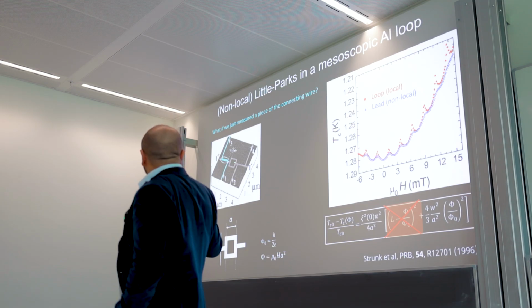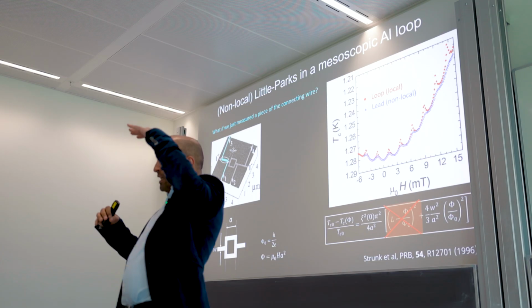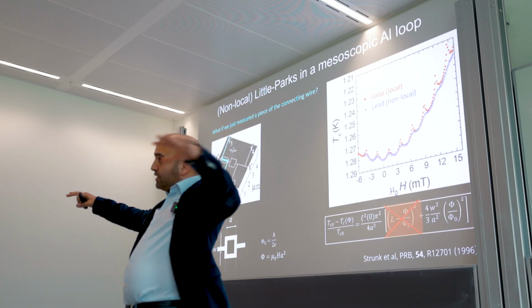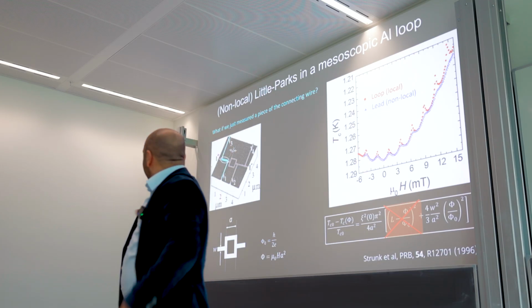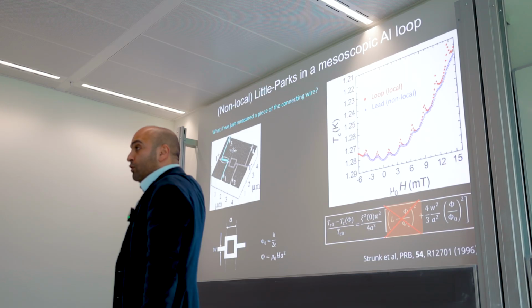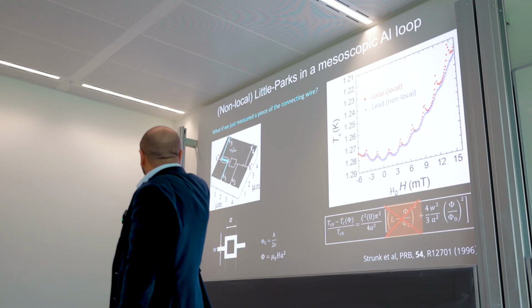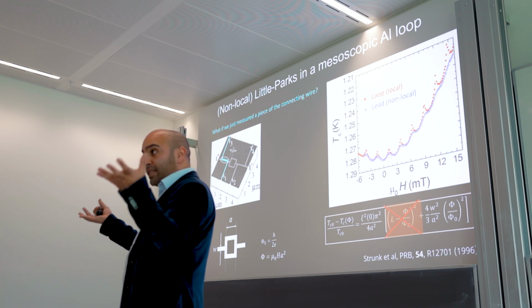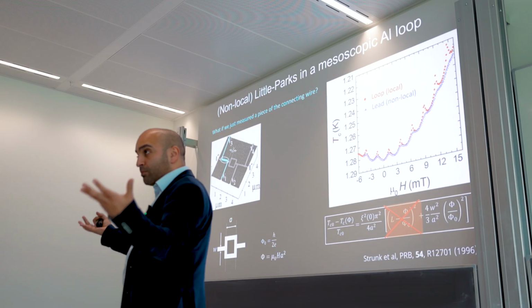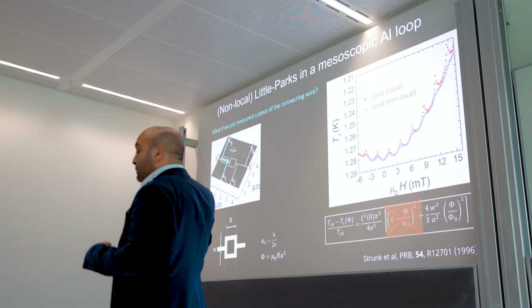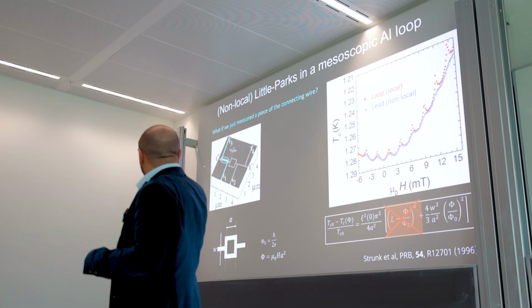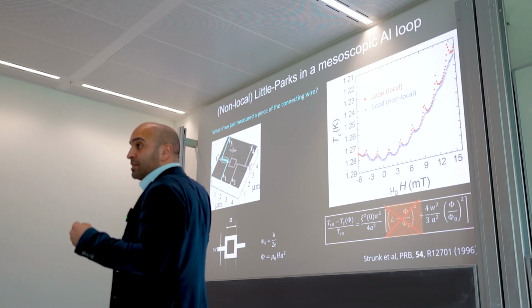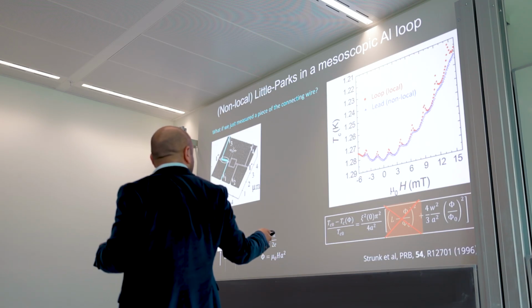So in this case, when your condensate gets weaker in the ring, that's not where the wave function ends. The wave function spreads way beyond that ring. So it also lowers the transition temperature of these parts because, again, the amplitude of the condensate, the density of Cooper pairs, the size of the gap, these are all very much related. So when the ring lowers its Tc, it also lowers the Tc of these leads. Yes? Is that why lower in the graph we see the peaks clearer, and higher it looks more like a parabola?